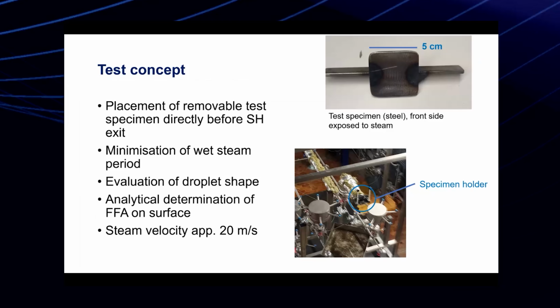For the test concept, we place this metal plate, around 5 centimeters by 5 centimeters. This is the test specimen steel, and the front side is exposed to the steam. We are doing the baseline first, so this specimen will be subjected to dry steam that is being treated with ammonia. Then we run it for 1 day, and after that we replace the test specimen and start with the Fineamin treatment. Then we put a different test specimen and see the absorption on the metal surface.